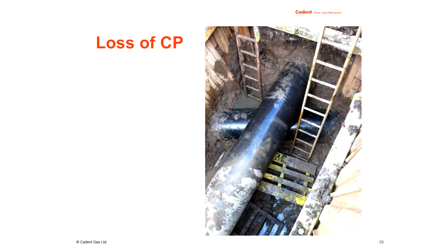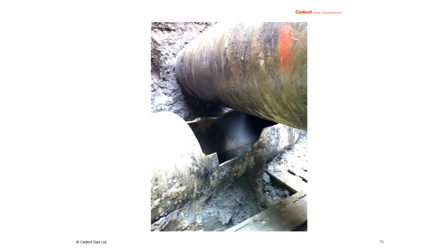And this is a 24-inch high-pressure pipeline that was constructed back in the British Gas days and laid directly on top of a water main. Luckily, that was another main that was decommissioned, so we could smash it out and restore the CP to the high-pressure pipeline.